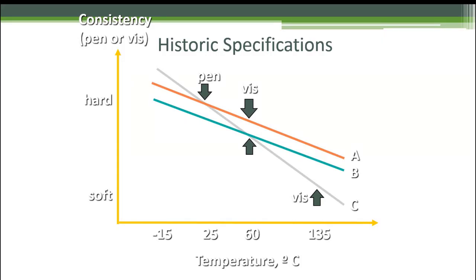Conversely though, is when it gets extremely hot in the summer, right? We run the viscosity at 60 degrees and kinematic at 135 degrees centigrade. So that's 140 and 275 basically. Is if I just use viscosity to grade it and specify it, I've got B and C, right? They meet the same viscosity specification requirement. And just as we talked about with pen graded, the problem here is that B is much more soft, C is much more brittle, and therefore susceptible to cold temperature thermal cracking.